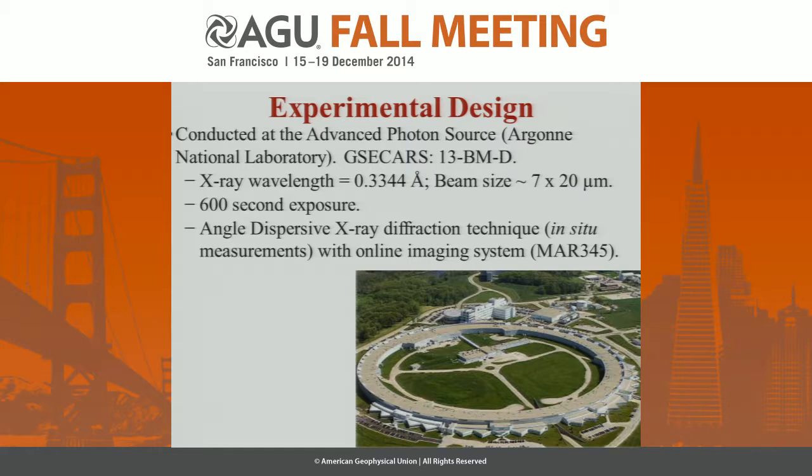We use the X-rays for a couple of reasons. One is to evaluate the phases that existed in the sample chamber, to see if it was just ice 7 or if we had other phases as well. We use the X-rays to interact with the gold, using the equation of state of Anderson et al., to get a pressure from that property. And the beam size is small enough for our relatively large sample chambers that we can move around the sample chamber and evaluate different parts of it, to make sure that there were no new phases in there as well.